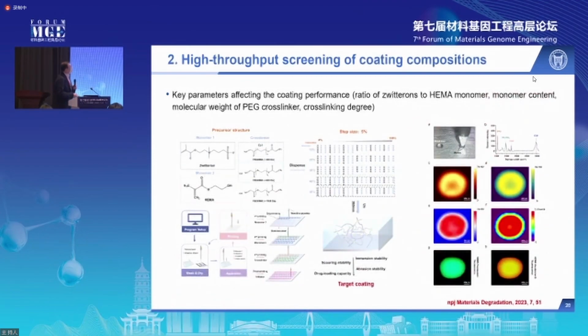And we can also use this similar technology to screen coating formulations. And this is showing that even with high viscosity resin, the composition within each droplet is still very homogeneous.